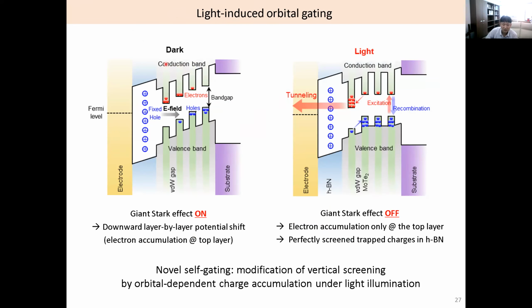So in the dark condition, as I said, we have some uncontrolled impurity charges in the hBN, and we have some electron accumulation like this. This is screening, okay? So as I said, we make a voltage drop like the previous MoS2 case. This is called the giant Stark effect. And if we illuminate light, by this voltage drop, by this electric field, electrons are moving in this direction. But these electrons cannot go into the electrode easily because we have this tunneling, insulating barrier. So only the top MoTe2 layer is strongly electron doped, and other layers are like this. Okay, so it will be an equilibrium situation.